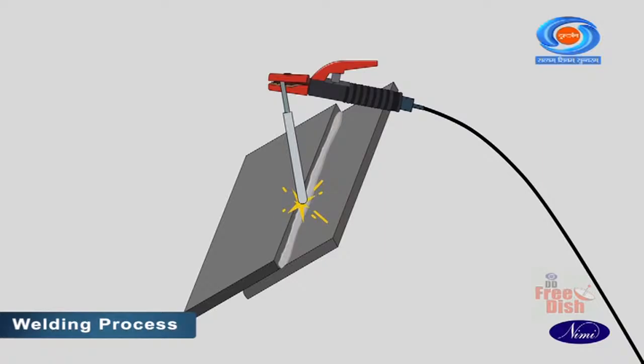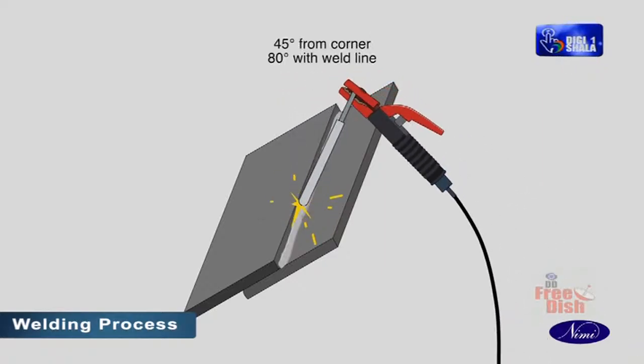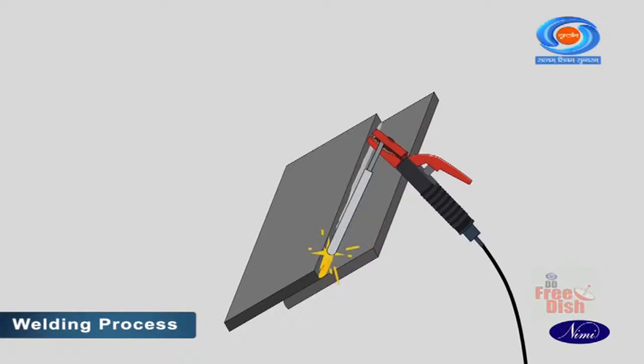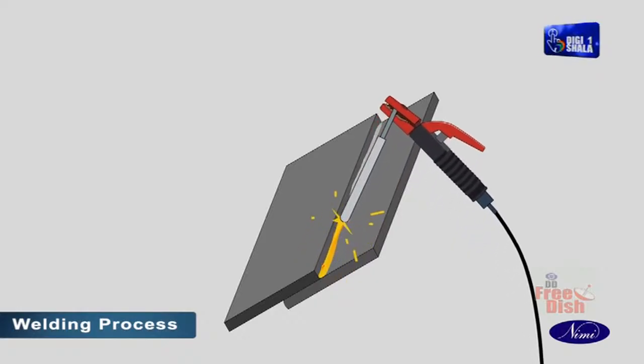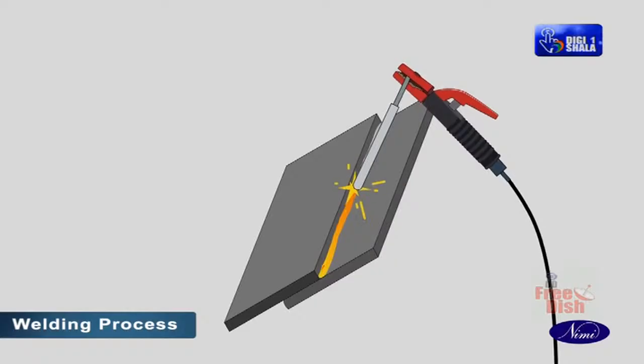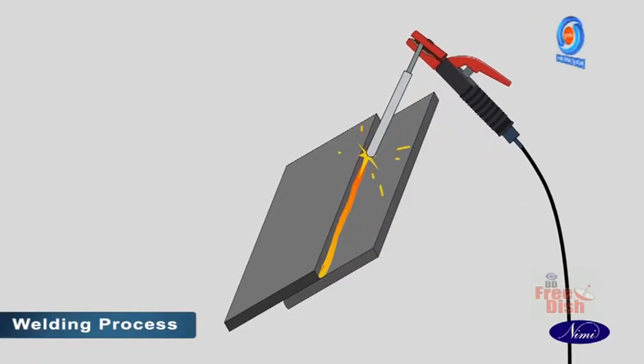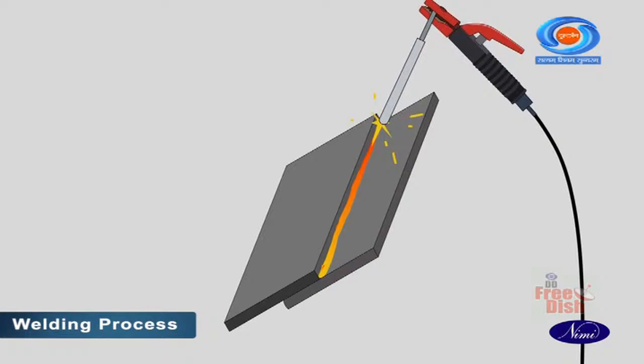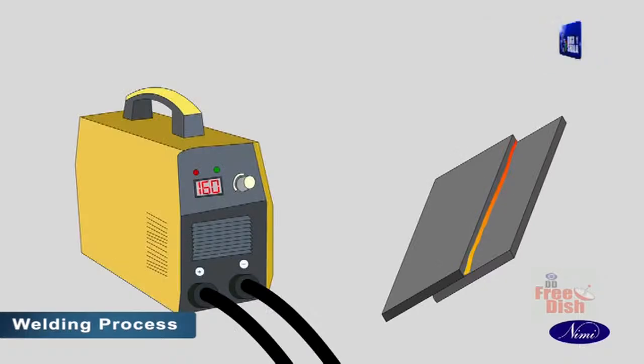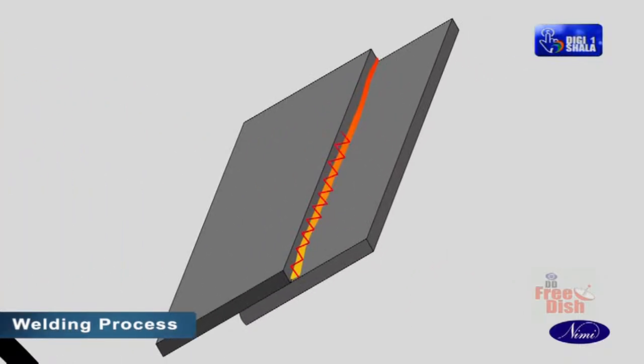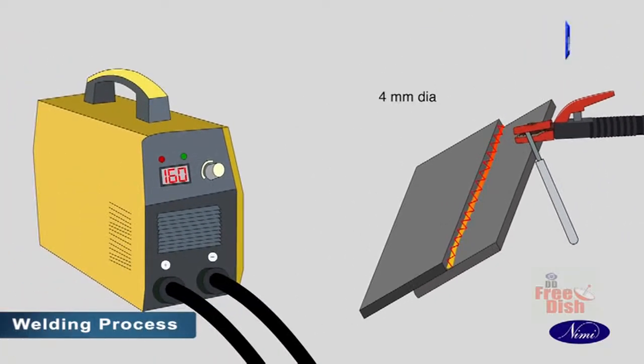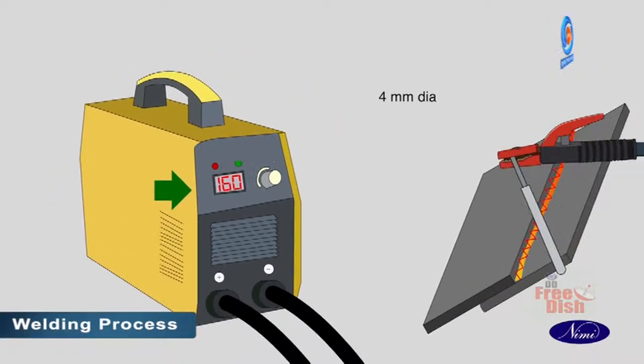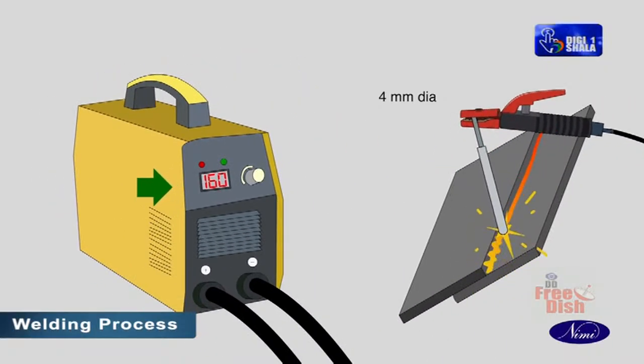Ensure an electrode angle of 45 degrees with the fillet corner and 80 degrees with the welding line. Maintain a short arc to get uniform fusion and root penetration and avoid side-to-side movement of the electrode. Deposit the final covering run with a weave motion using a 4 mm dia medium coated MS electrode with 150 to 160 amps welding current.